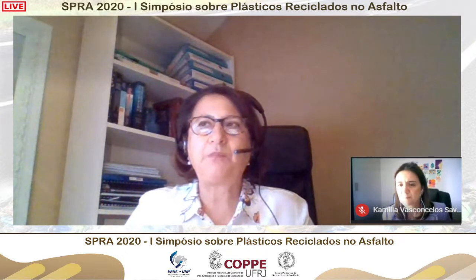Yes, I did, and I showed it. Should I show it again? In one of the slides, I did show this. There's a microstructure of the binder modified with plastics, and there was a microstructure of the mixture. Should I share this, or will you have this? It's on slide 22. Okay, since everything will be recorded, everyone can go back to the recording after the presentation. I think it's better. Yes. So the binder with the plastic was imaged using an electron microscope, and we do see a difference in the binder without plastic and the binder with plastic. Even though it was added above the melting temperature of the plastic, it still shows up in the microstructure. Also in the mixture microstructure, it did show up.